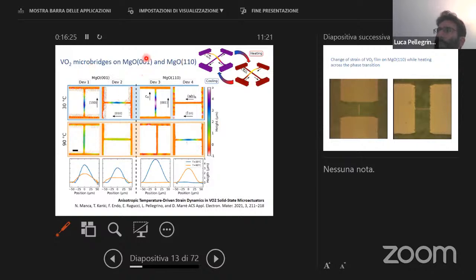where we fabricated microbridges onto different MgO substrates, and this one is on MgO 001 at low temperature. This is an optical profilometer image. This is freestanding vanadium dioxide. At low temperature, the film is bent in the two directions due to the fact that the films are slightly compressed.